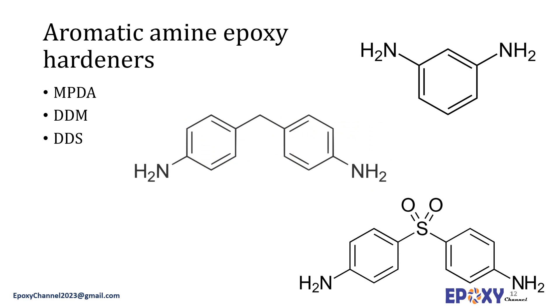The next group is aromatic amines, used as curing agents for epoxy systems. The advantages of aromatic amines over aliphatic amines include the development of a higher heat distortion temperature in the cured product and greater chemical resistance after cure. The mixture needs to be cured with heat to achieve excellent elevated temperature performance. Aromatic amine-cured epoxy systems can give films with excellent gloss, blush-free surfaces, and excellent chemical resistance.